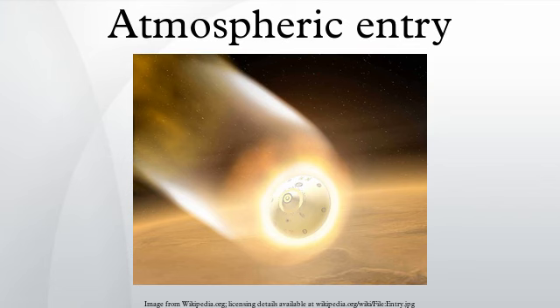SIRCA, silicone impregnated reusable ceramic ablator, was also developed at NASA Ames Research Center and was used on the back shell interface plate of the Mars Pathfinder and Mars Exploration Rover aeroshells. The BIP was at the attachment points between the aeroshell's back shell and the cruise ring. SIRCA was also the primary TPS material for the unsuccessful Deep Space 2 Mars impactor probes with their 0.35 m base diameter aeroshells. SIRCA is a monolithic, insulating material that can provide thermal protection through ablation.